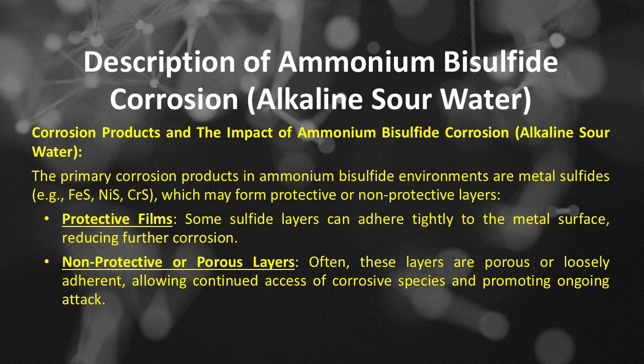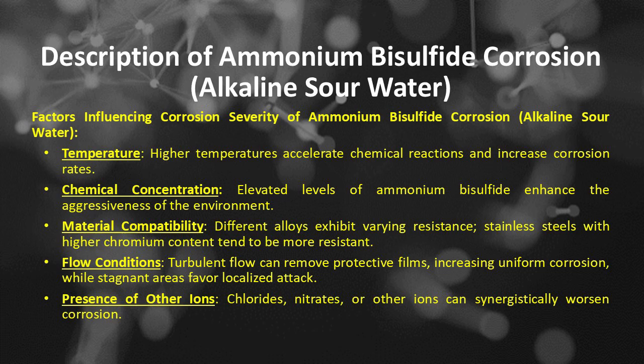ongoing attack. Factors influencing corrosion severity of ammonium bisulfide corrosion or alkaline sour water include temperature. Higher temperatures accelerate chemical reactions and increase corrosion rates. Chemical concentration. Elevated levels of ammonium bisulfide enhance the aggressiveness of the environment. Material compatibility. Different alloys exhibit varying resistance. Stainless steels with higher chromium content tend to be more resistant. Flow conditions. Turbulent flow can remove protective films, increasing uniform corrosion, while stagnant areas favor localized attack. Presence of other ions. Chlorides, nitrates, or other ions can synergistically worsen corrosion.